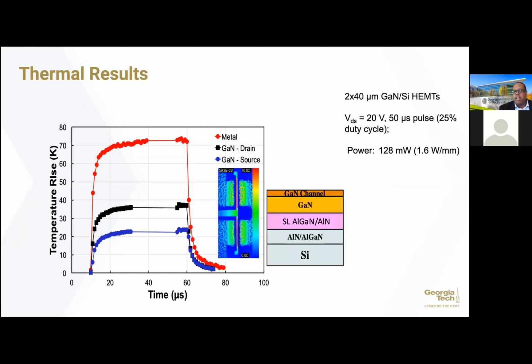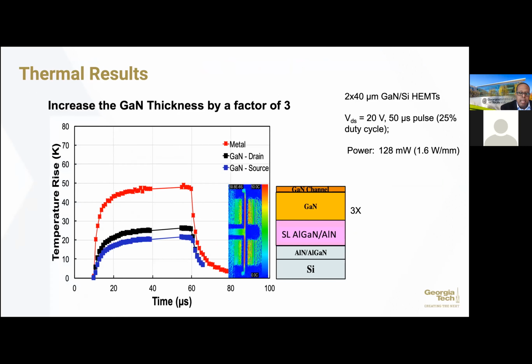And so here are the results. When I have this particular structure with a superlattice structure here, I'm fixing, say, this gallium nitride layer. You can see the temperature rise here is on the order of about 70 degrees C. If I increase that GaN layer thickness by a factor of 3, you can see it drop. And so this is one of the signs that shows you that, yes, you can build in this heat spreading. You can do this co-design based on thermal resistance, stresses, and heat spreading inside of the device architecture.